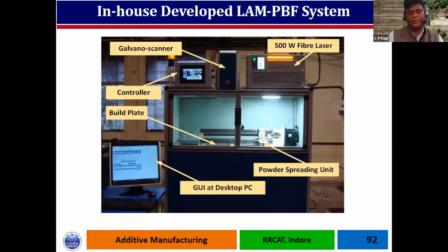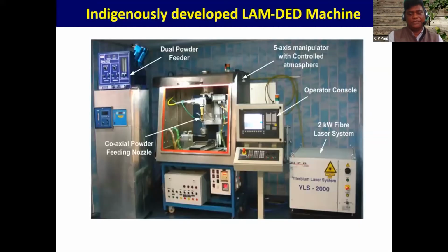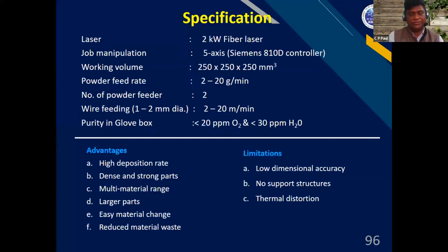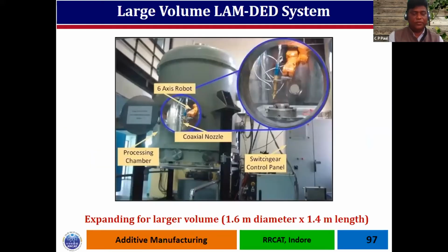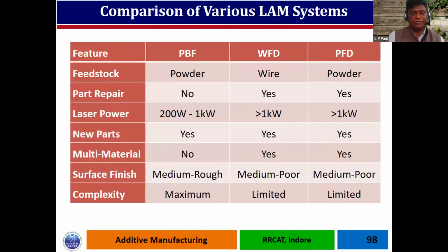So that is required for things to happen in the country, to take things leap to another level. Similarly, if we talk of the DED machine, the commercial machine will cost somewhere 5 to 7 crores. And when we did this in the country, we did it with an investment of around 2.5 crores. That is a big change in the whole scenario. We're increasing the volume, going for larger components, larger shapes. Now we can have a large volume like 1.6 meter diameter and 1.4 meter length. The component can be built on this size.